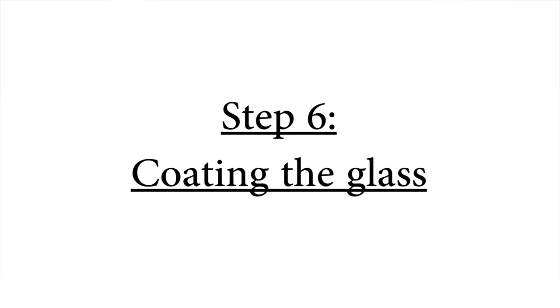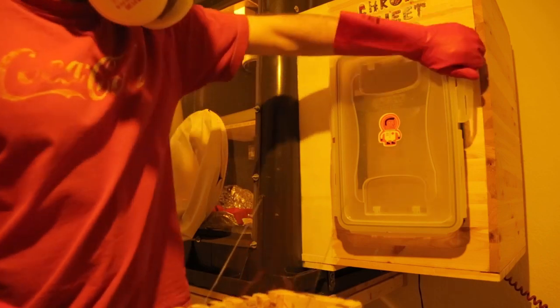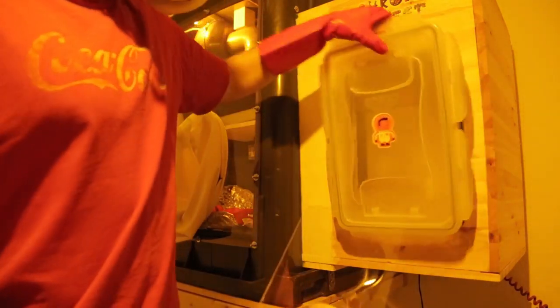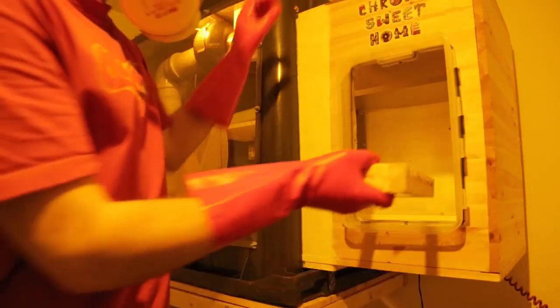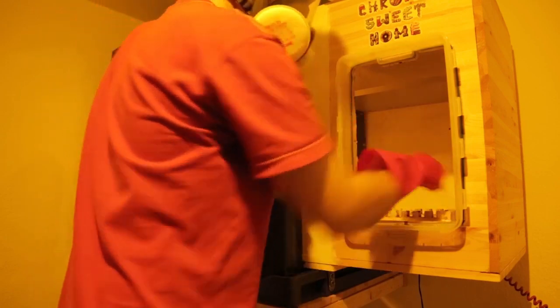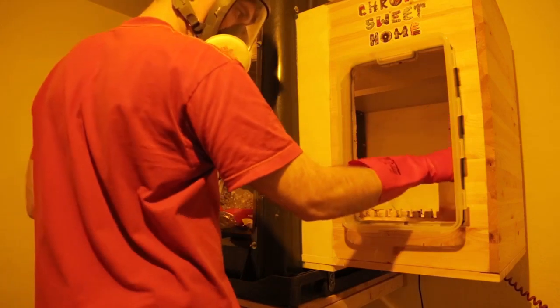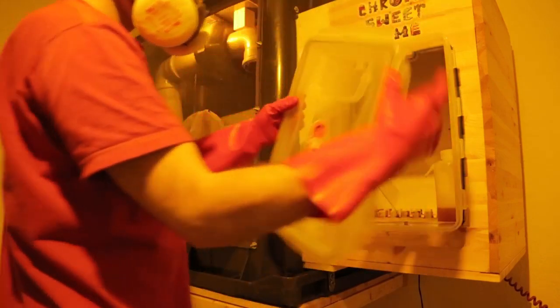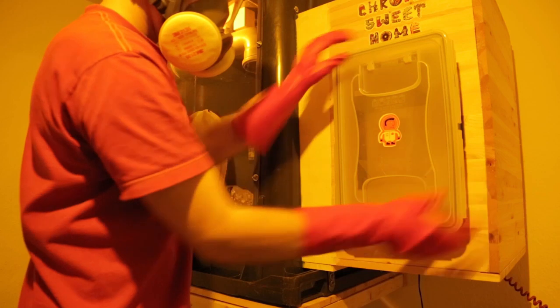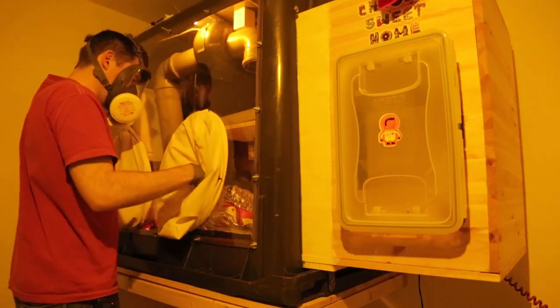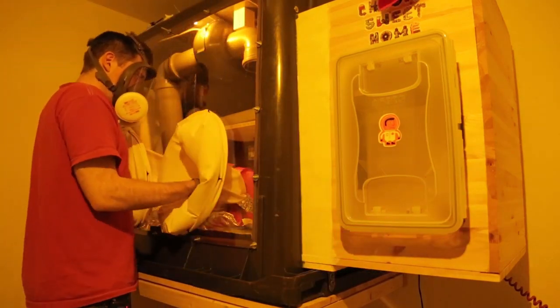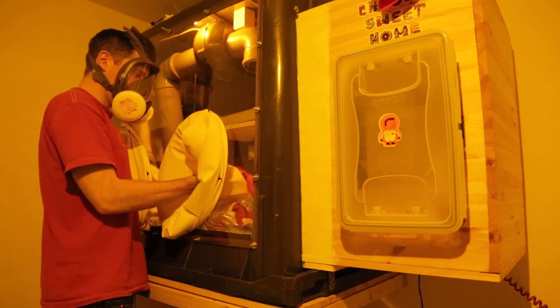Step 6. Coating the glass. For the purpose of coating the glass plates, I've built a second glove box. It's actually a dumpster turned upside down with an acrylic glass front and an airlock attached to the side. I take a warm, clean glass plate out of the drying cabinet and place it together with the coating bottle inside the airlock. The glove box guarantees a controlled coating environment that is dust-free.